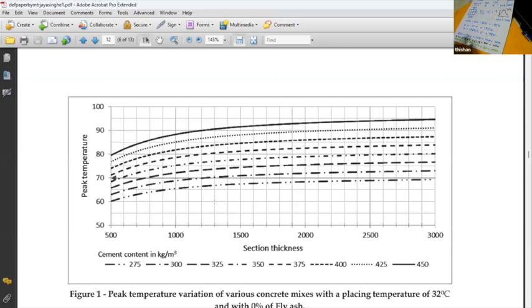So we need a mix of 350, but we don't call it cement now, we call it cementitious material. So we'll have a cementitious material of 350, where cement is only 275, and fly ash is 75. And what can you ensure? You can ensure that concrete will never exceed 70 degrees. On the other hand, let's say we have to use 300 kilograms of cement, and we are using 75 kilograms of fly ash, coming closer to a 25% ratio.